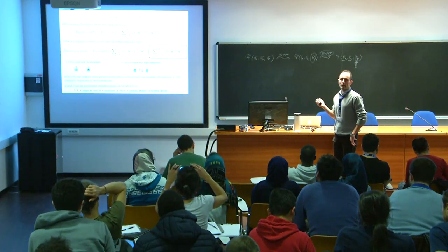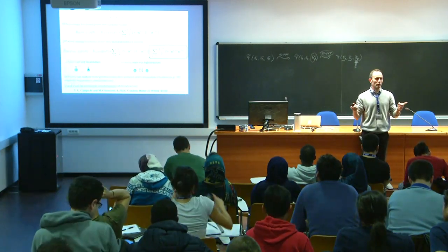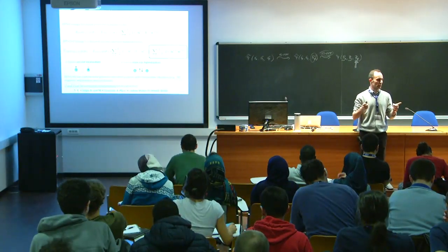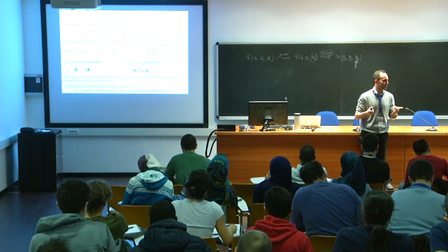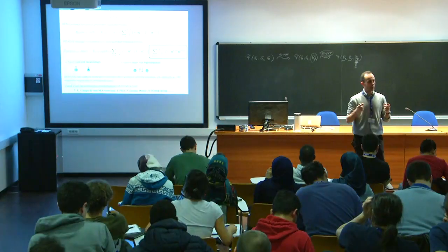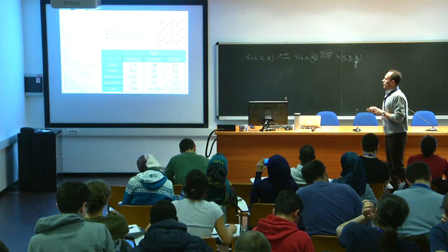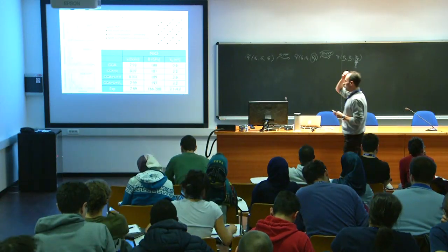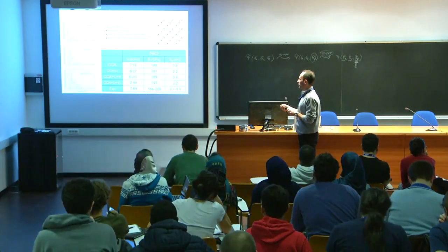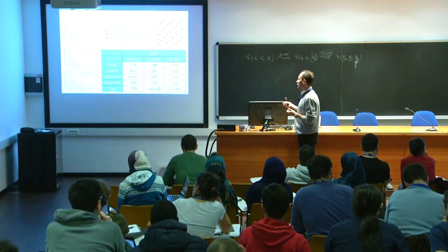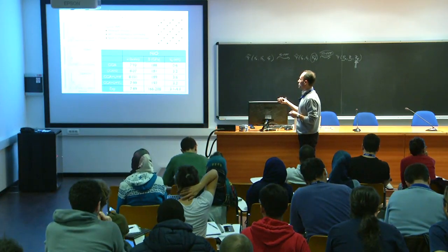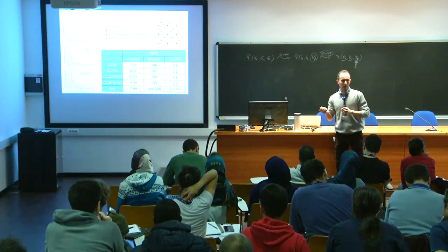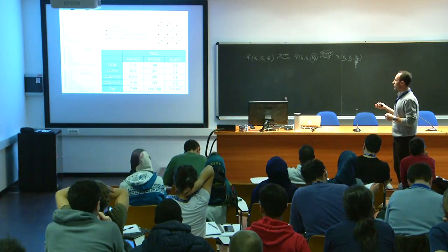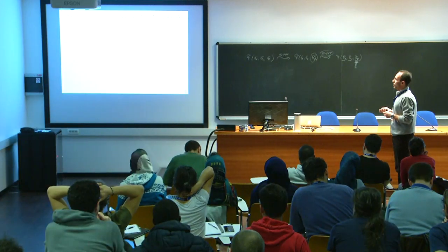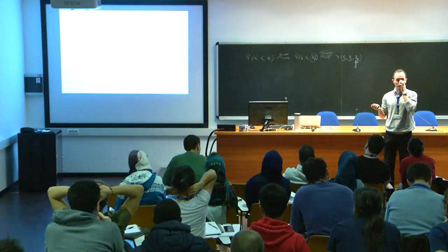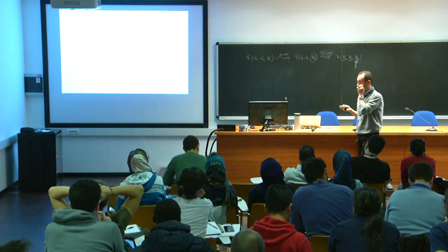This is just the off-diagonal term of that same interaction matrix, of which the U is the diagonal term. Okay, so it's nothing new, and this comes out for free, basically. So how does it work? Well, we tried first nickel oxide, which is a case where the standard one already works relatively well, and you get a small refinement on the equilibrium lattice parameter and bulk modulus, but the gap is of the same quality. Silicon and gallium arsenide, those are the ones that we care the most about with this correction.